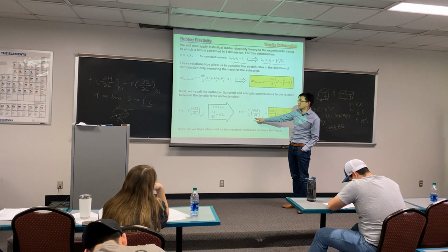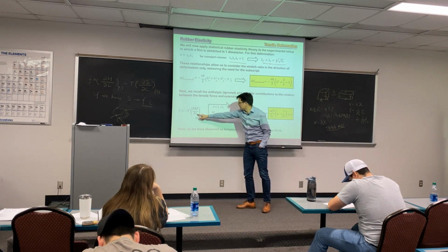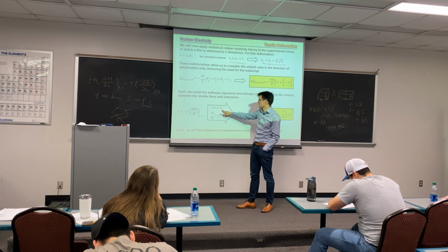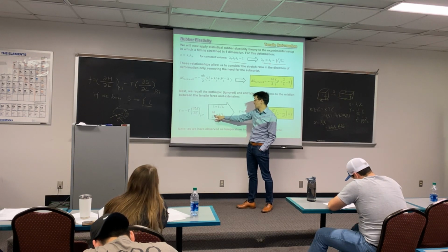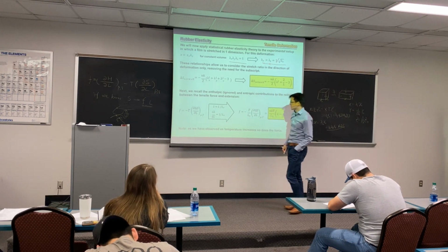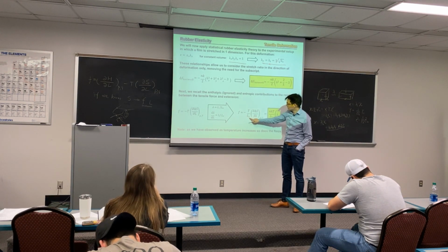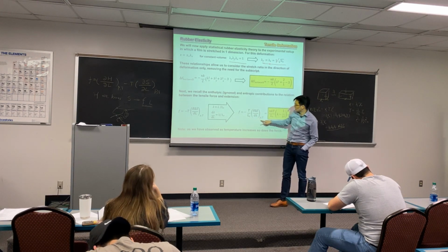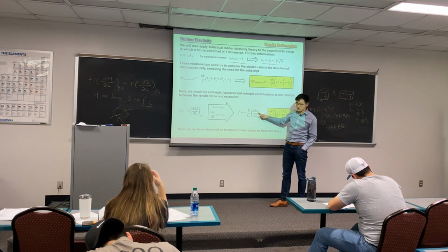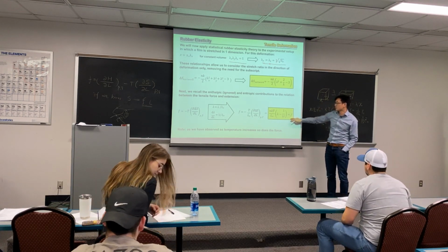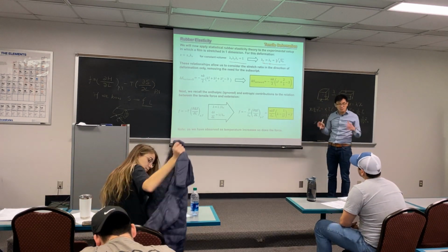It's very straightforward. L is related to lambda by a constant factor of L0. So partial derivative of lambda versus partial derivative of L just differs by 1 over L0. So if we put an L0 in the bottom of your equation, you can rewrite the force as entropy change, partial derivative of lambda. And we already know what this value is. So that predicts